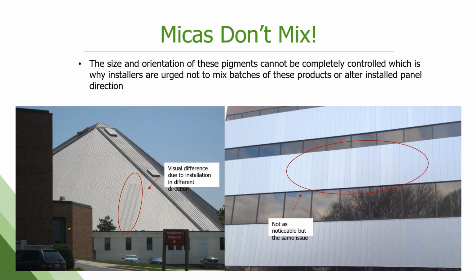like we're currently doing an Intel project that's like 12 or 14 buildings that are all a silver metallic. A lot of material that has to be run at one time. But this is kind of what it looks like. So you can see the picture on the right is actually different batches that were mixed. And then the picture on the left is they are directional. So the orientation of that panel makes a difference on how the color appears. And if you flip 180 by accident, it's going to show up as a different color on the job site.